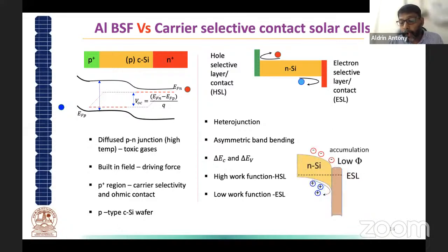And this is when it comes to low work function materials, where when the Fermi levels align, because the work function is lower here, the band bends down and the electrons here can move easily to the low work function metal or material, and the holes will be blocked here because of this band structure. Okay. So this is how the carrier selectivity works, and only the electrons will be moving in one direction and holes in the other direction.